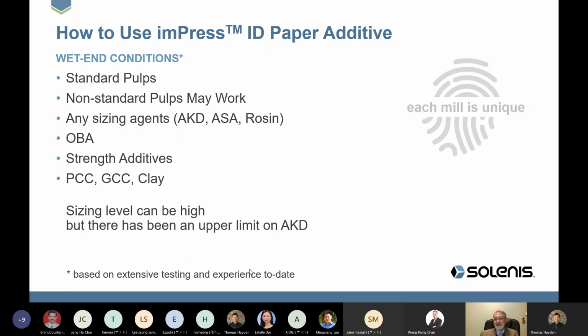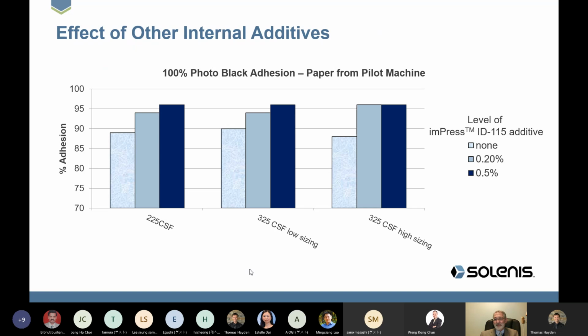I think the only time we've seen any issues is when somebody has used an extremely high level of alkyl ketene dimer, AKD. And that is because AKD is unique in the sizing world in that it can crystallize on the surface of the paper and give a very hydrophobic, very low surface energy. But I'm talking about paper that maybe have hundreds or even several hundred seconds of sizing. And almost nobody does that anymore. AKD can be so effective, it can even hold out color inkjet inks and even have them bead up on the surface. So if you overdo it, you can get some issues. And if you're interested, we can talk some other time about the differences of wet end chemistry and what it makes a difference in the size press.